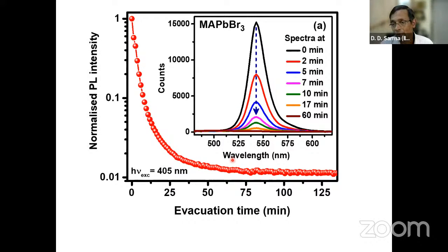But the problem turned out that even if I'm not changing the temperature, but only doing the measurement as a function of time, I find that the intensity is going down very rapidly. The reason is that to do this experiment as a function of temperature, you have to put the sample in a cryostat and evacuate it. If you didn't evacuate, then when you lower the temperature, all the moisture, oxygen, and nitrogen will condense on top. But as you evacuate, some defects get created because you're sucking something out of the sample. The intensity drops to 1%, from here all the way down to almost zero. And that had to be avoided.